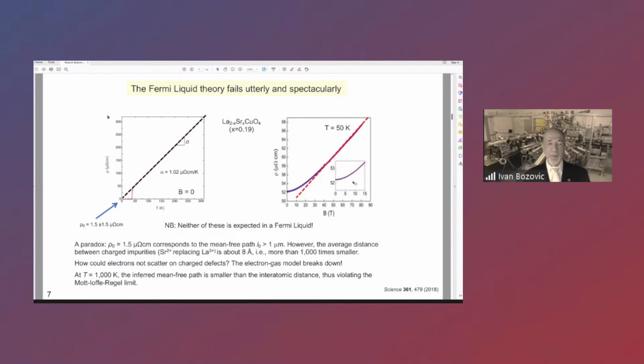Here is an example of a very good lanthanum strontium cuprate film grown by molecular beam epitaxy. And what you can see is that resistivity is linear in temperature up to 1000 Kelvin, which is not shown here. This is quite unexpected because in a standard metal, resistivity should go as a third or fifth power of temperature, and then it should curve upwards, and then it should saturate at higher temperature. And more disturbing, if you use a Drude model and calculate the mean free path from this model, then you will conclude that at this highest temperature, the mean free path is shorter than the interatomic distance.